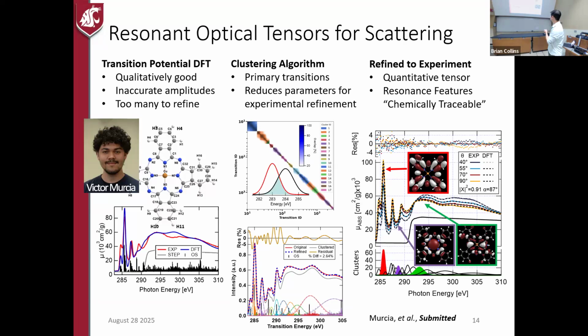For example, this tall one is just the petals, the exterior petals of this copper phthalocyanine molecule. This transition is just the metal center. And then this transition up here is the isoindole, so it's the nitrogen-carbon bonds that we're interacting with. So now we can use this a little bit like Raman spectroscopy, in that we're trying to characterize what part of the molecule we are focused on for each of these peaks when we're using that X-ray measurement. That's really exciting.